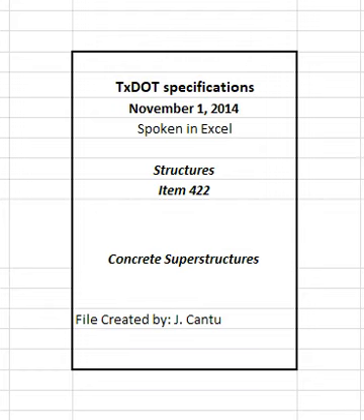4.6.1 Placing temperature. Place superstructure concrete only when its temperature at the time of placement is between 50 degrees Fahrenheit and 85 degrees Fahrenheit. Increase the minimum placement temperature to 60 degrees Fahrenheit if slag cement is used in the concrete. 4.6.2 Transporting time. Begin the discharge of concrete delivered in truck mixers within the times listed in Table 14 of Item 421, Hydraulic Cement Concrete.